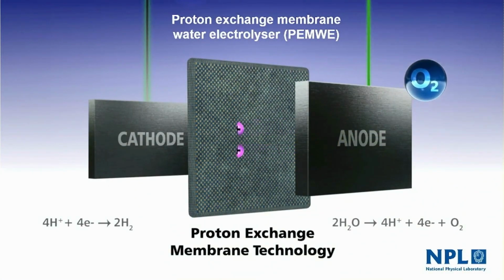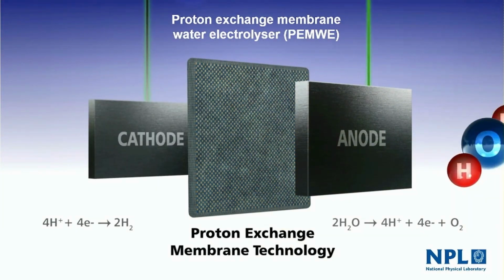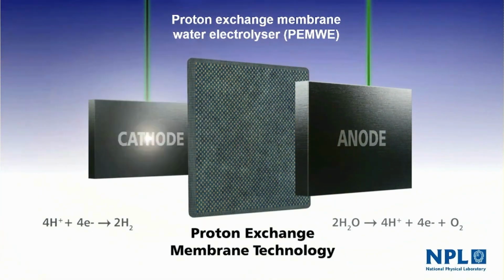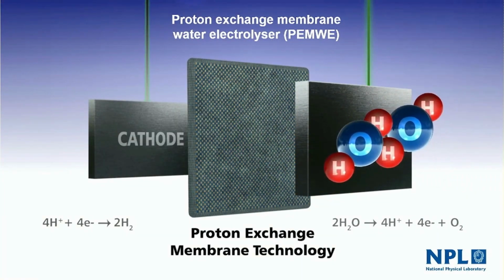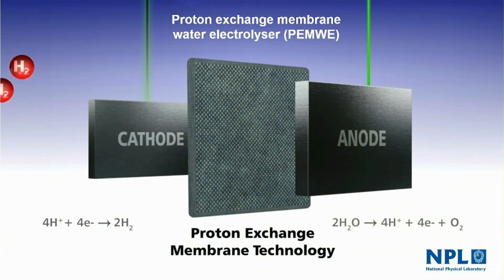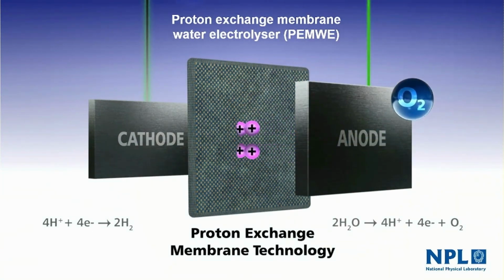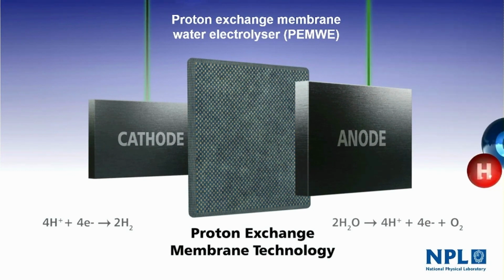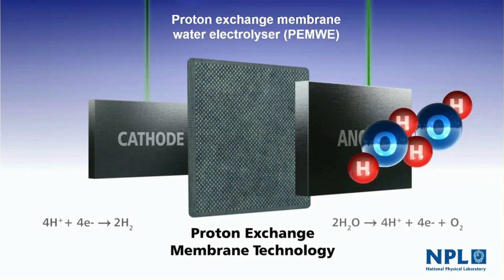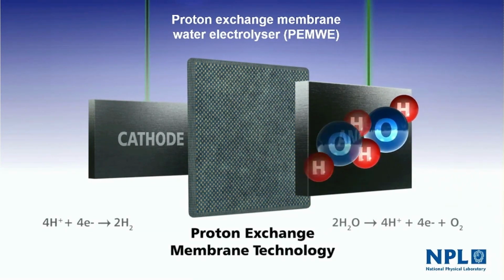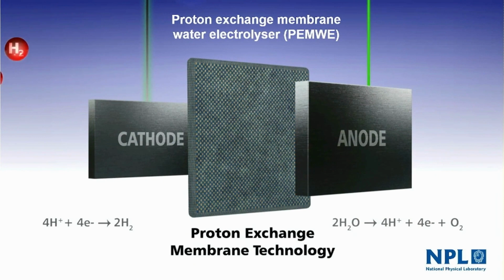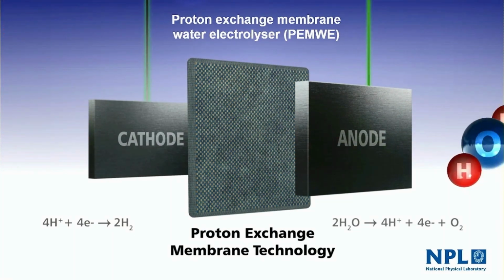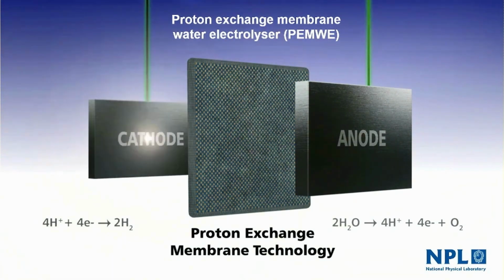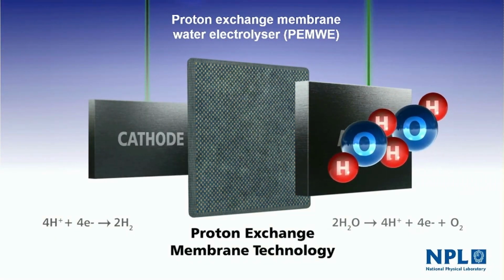This is how an electrolyzer works. So this is a very special material. It's a proton-conducting membrane that's electron insulating. And when you supply water to the anode and apply a potential of about 2 volts between the anode and cathode, you oxidize water to form oxygen. Protons then migrate through the membrane to the cathode, where they react with the electrons to form hydrogen. And you can collect and store this hydrogen in a big tank at 1,000 bar of pressure and dispense it to vehicles. So this is a reasonably new technology. It's been developed in the UK by ITM Power, who manufacture the refueling station that's on our Teddington site, and many others throughout the world. And they're one of the top 3 companies in the world manufacturing this type of water electrolyzer, which is a proton exchange membrane, or PEM water electrolyzer.